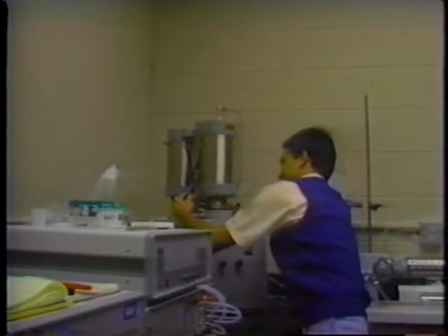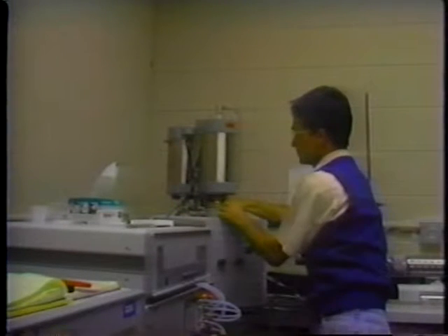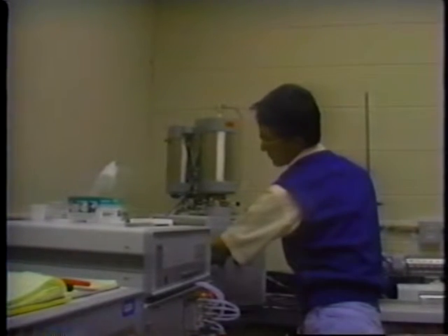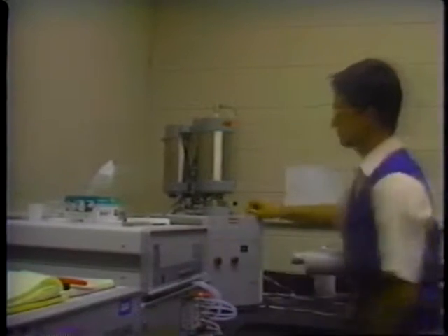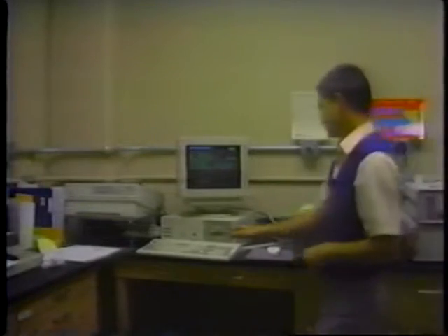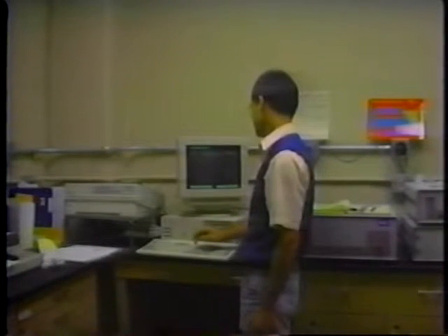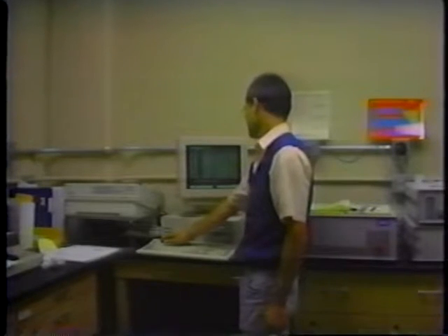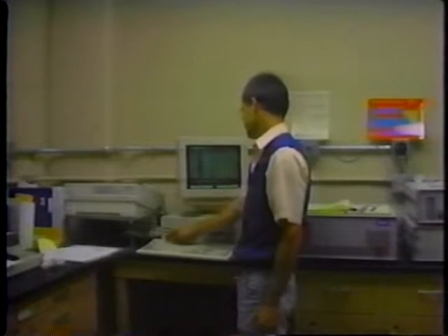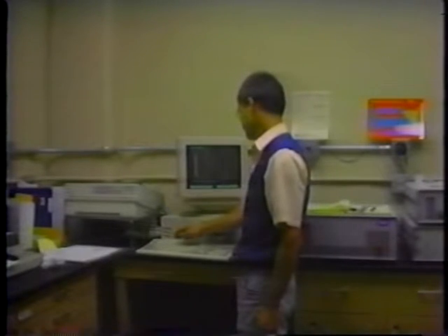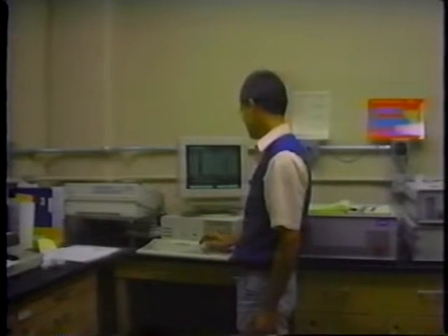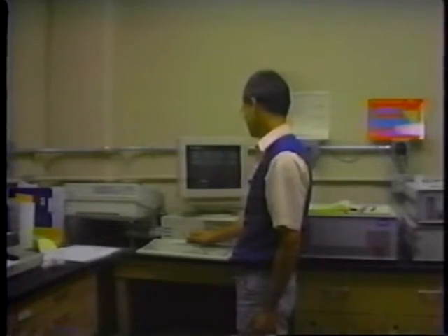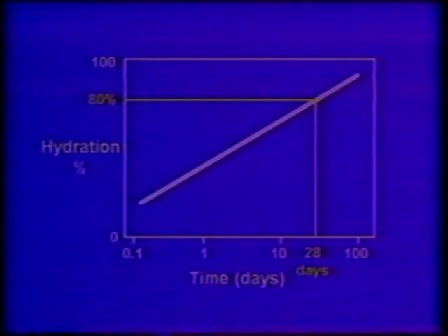The free water in a sample is driven out by heating to 105 degrees Celsius. At 105 degrees, the sample is dry but still retains its strength. The water involved in the hydration reactions is chemically combined with the cement and can be driven out of the sample by heating to 1,000 degrees. At 1,000 degrees, all of the original mix water has been removed from the sample. The degree of hydration is calculated from the weight of chemically combined water. A typical cement paste cured in moist conditions will reach a degree of hydration of about 80% in 28 days.